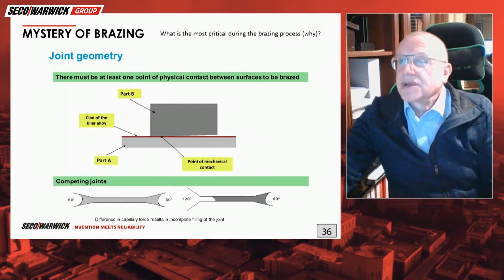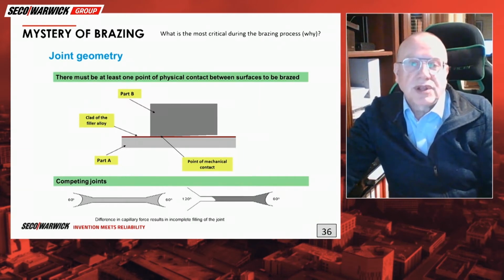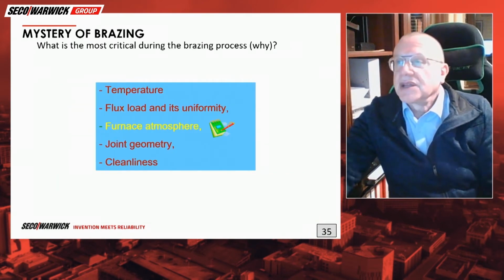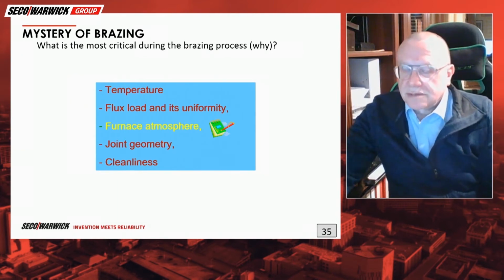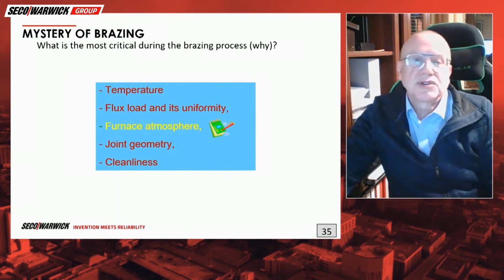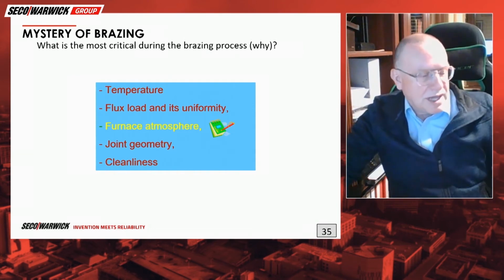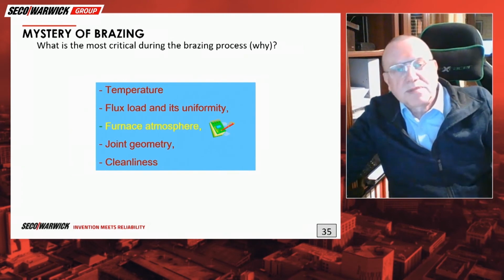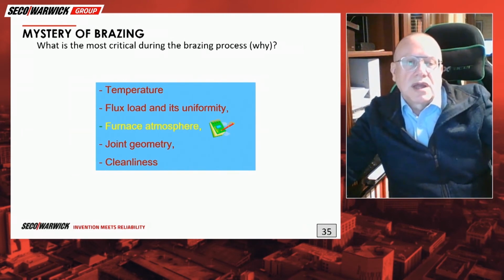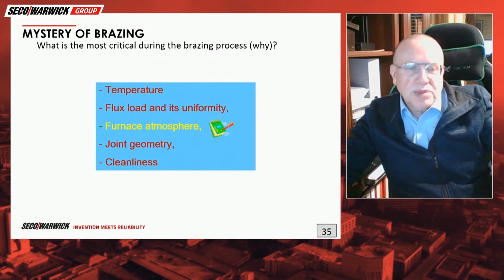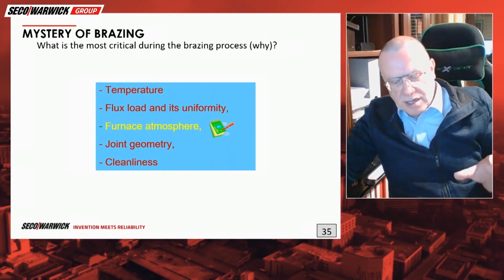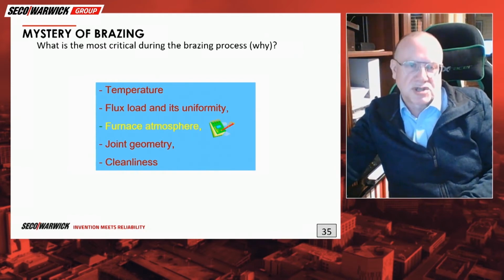The next factor is furnace atmosphere. Again, I'm talking about furnace brazing, and here we can have either vacuum furnaces or continuous furnaces. With continuous furnaces, we have the ends of the muffles, which could be as much as 20 meters long, open. And we pump in an inert gas. The flow of that inert gas decides the content of oxygen inside the brazing zone.